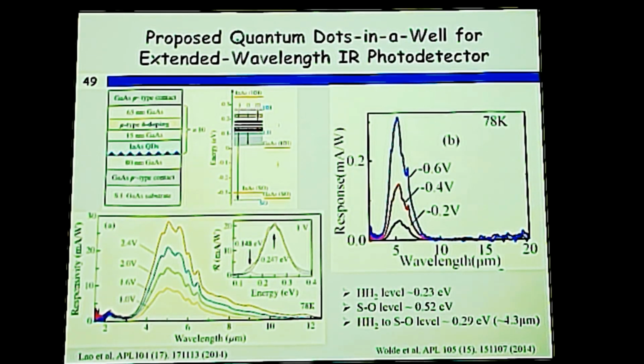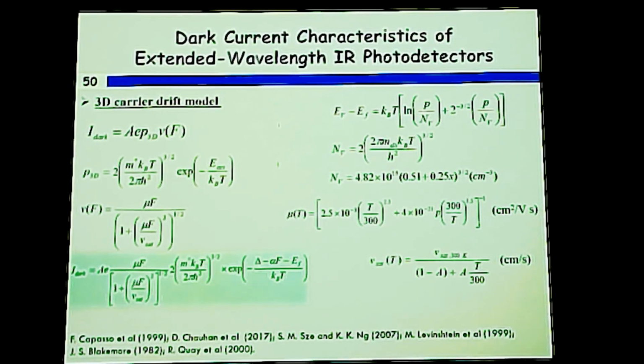So in the next, I'm going to show you the dark current characteristics. We use a 3D model to fit the experimentally measured dark current, using the electrically active area, not the optical. This term P is the thermally excited carrier density. V is velocity, which depends on the applied field, and the model becomes this, where this Fermi level is measured for p-type, with the valence band edge as the reference 0, and that depends on the doping level and